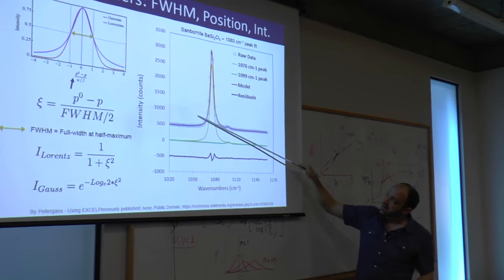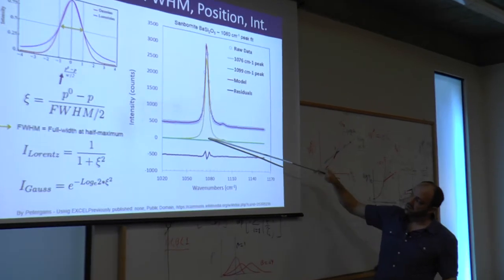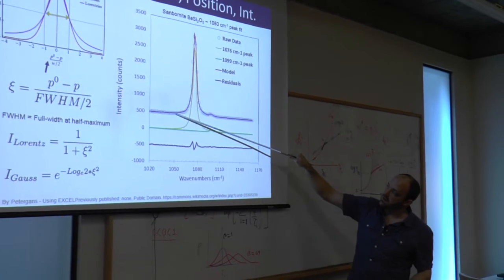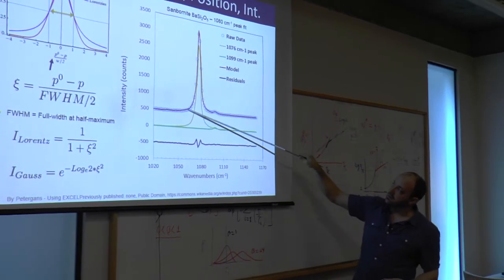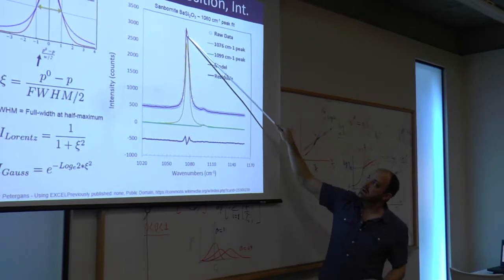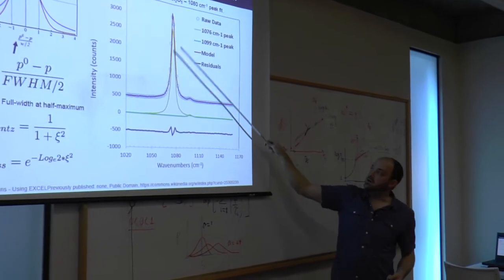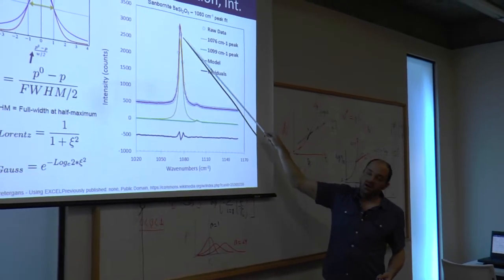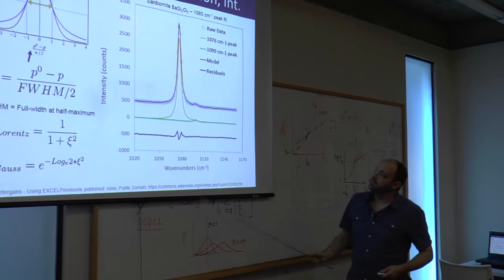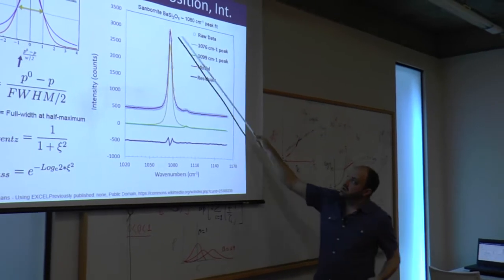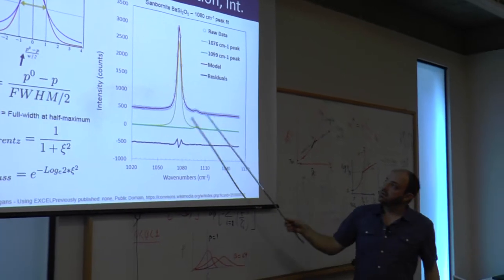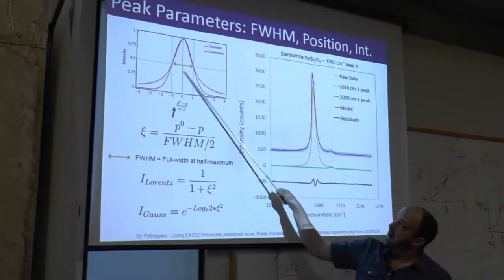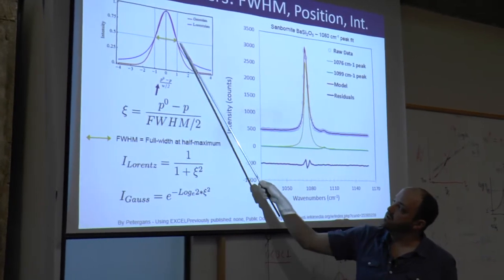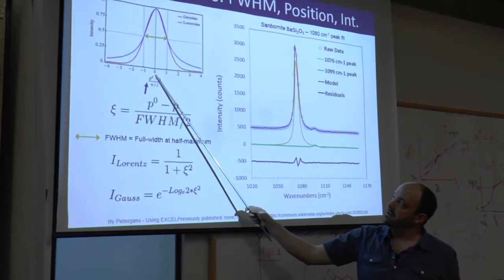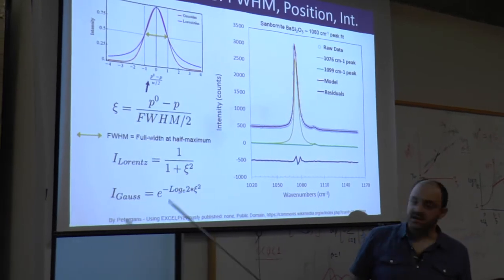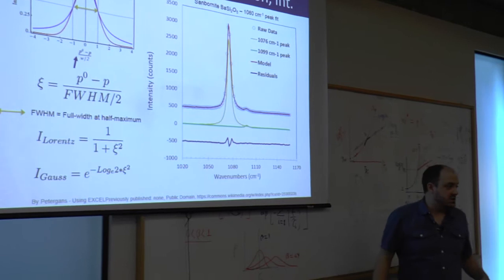So you'll see that the model, which is just the sum of the yellow plus the green curves, becomes this red model. It goes right through the center of my actual data points. And you can see that there's some mismatch right at the top because our spectral resolution is limited to a couple wave numbers, but the peak is in between there. So we normalize this peak to 1, and then you can measure the width at half of the maximum intensity. This is the full width half max. And then you can look at the shift in the wave number as you go away from the center. And these are the equations for actually calculating the shape of that line.